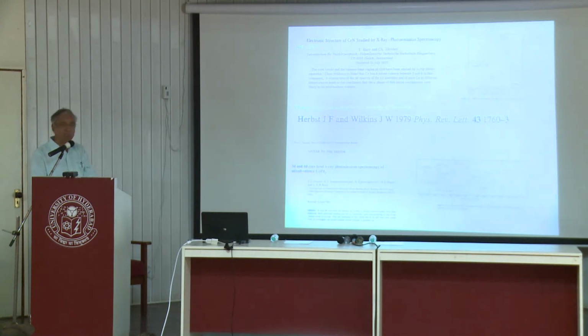Let me skip that. I just want to mention that we were one of the early birds to get into this field. In those days we did not have photoelectron spectroscopy here. We used to go to IIT Bombay, and I also collaborated with CNR on photoelectron spectroscopy. We found new materials where there is actually a spontaneous fluctuation of the 4f electron between the valence and local 4f orbital and the conduction band.